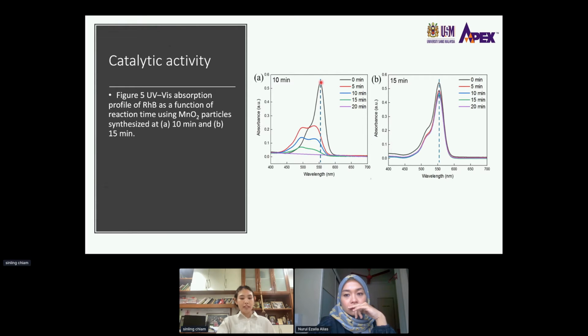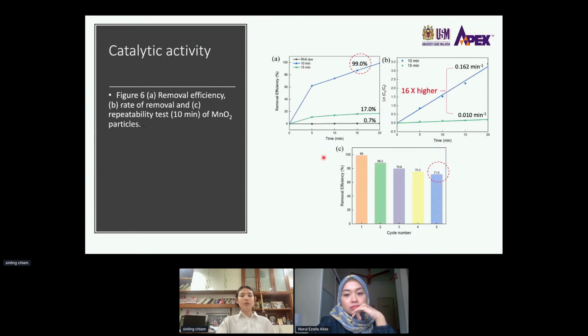We can see that the relative intensity of the absorption peak of MnO2 synthesized at 10 minutes nearly vanished after 20 minutes of reaction time. So the removal efficiency is quantified in this plot. The degradation efficiency of MnO2 particles synthesized at 10 minutes is 99%, whereas for 15 minutes it is only 17%. So the degradation process actually follows pseudo first order kinetics. The efficiency of MnO2 synthesized at 10 minutes is actually 16 times higher than that of synthesis at 15 minutes.